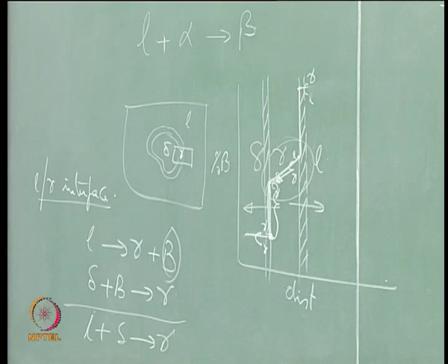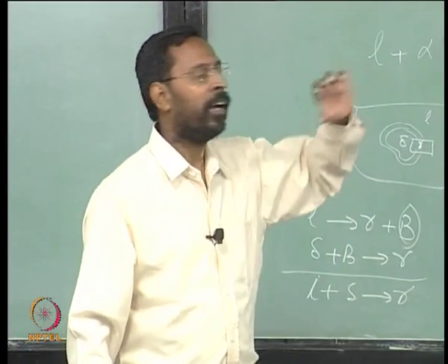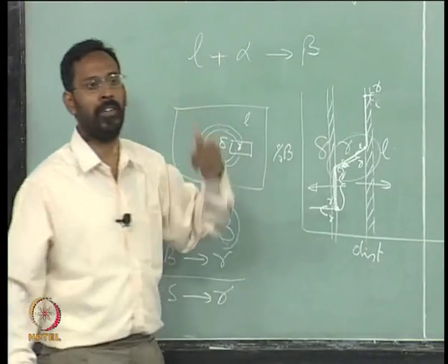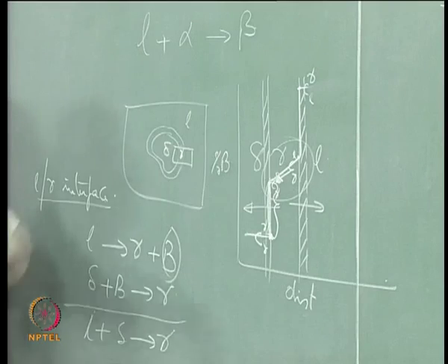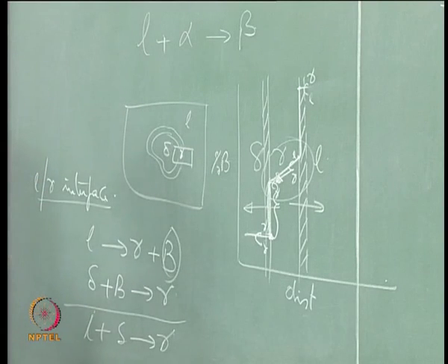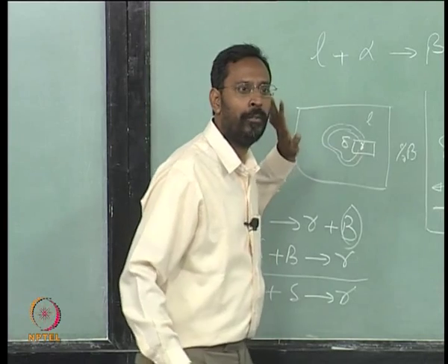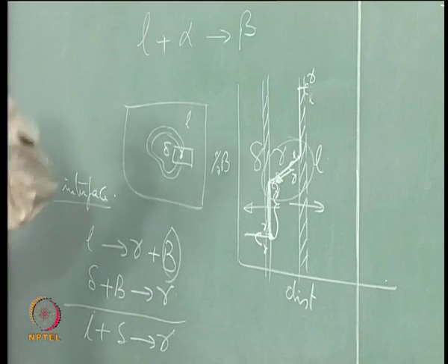We do not call it anymore a reaction, because there is no reaction here. So, the peritectic reaction that we traditionally call is only at the beginning. At the beginning you have a reaction, because there is a real interface between the liquid and the solid phase, and there is a reaction that takes place, and once the reaction takes place, the third phase, which is the product phase of the peritectic reaction, comes and covers the solid that is already available, and once this covering takes place, then the further reaction can only occur by diffusion.